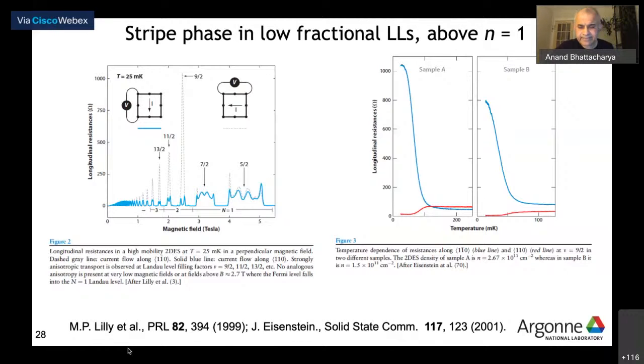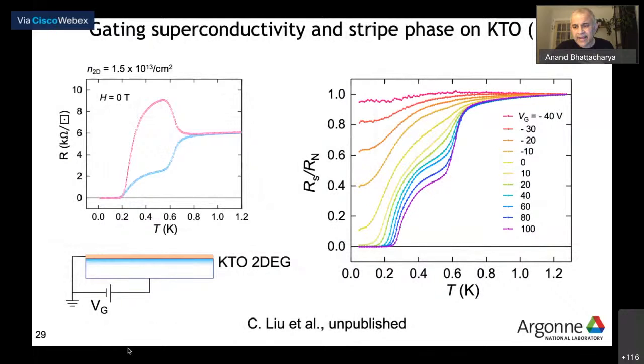Of course, there's a two-dimensional electron gas, so we're very keen to gate this thing, and so we did. We haven't published this yet. This is a different sample, by the way. If you look at the density, it's quite low, like 1.5 times 10 to the 13 per centimeter squared. And there, if you gate it, what you find is that the easy direction, the place where the superconductivity happens, actually gets pushed down in temperature, then eventually swept out.